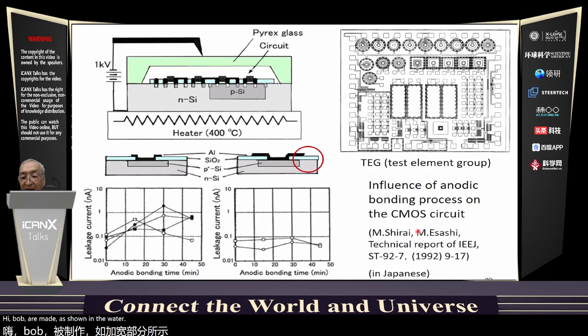The influence of the anodic bonding process on the CMOS circuit was studied using the test element group shown in the upper right. The principle of the anodic bonding is shown in the upper left. Negative high voltage is applied to the glass at around 400 degrees centigrade, and the glass and the silicon are electrostatically bonded at the interface. We found that the leakage current is caused at the exposed PN junction. However, this could be solved by shielding the PN junction surface with a metal layer, as shown in the lower left.